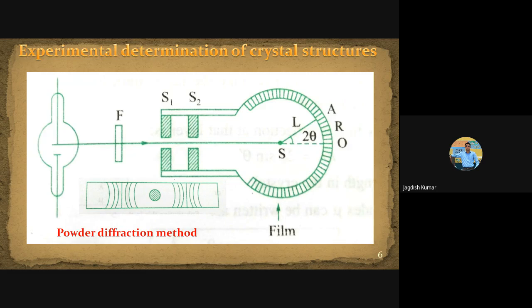So in our model, we have chosen the lattice parameter, which may be referring to the c axis, because we are talking about the 001 peak. So actually the length which we have taken for the c axis is smaller, because d is smaller. That is why theta is calculated at a higher angle. Then our model fixes that value of c in such a way that the two peaks match each other, and that is how this kind of matching is done by the software.